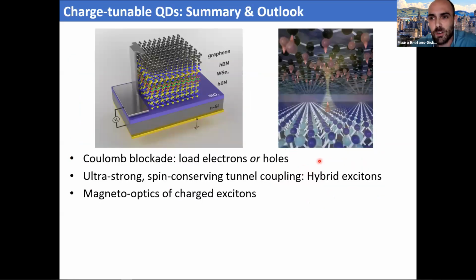So I hope I wasn't too fast with this part. Just to wrap up the results of this first part of the talk, I hope I convinced you that it's possible to achieve Coulomb blockade in a two-dimensional quantum dot. With a device like this, it's possible to have controlled tunneling of both electrons and holes in the same device. Due to the fact that we used an atomically thin tunnel barrier, we had ultra strong and spin conserving tunnel coupling, which led to the observation of hybrid excitons. And thanks to this device, we're also capable of studying the magneto-optics of charged excitons for the first time.